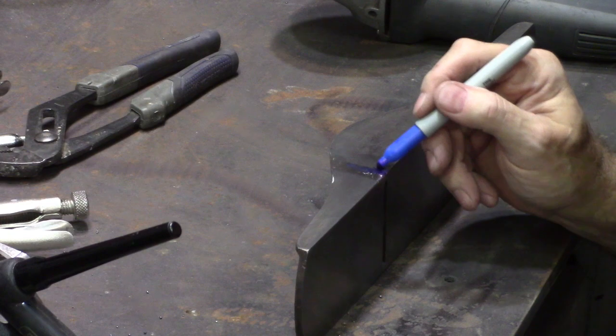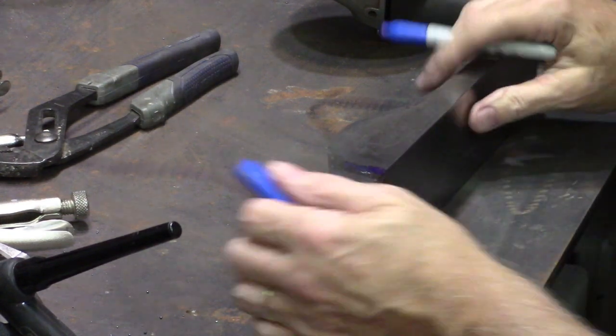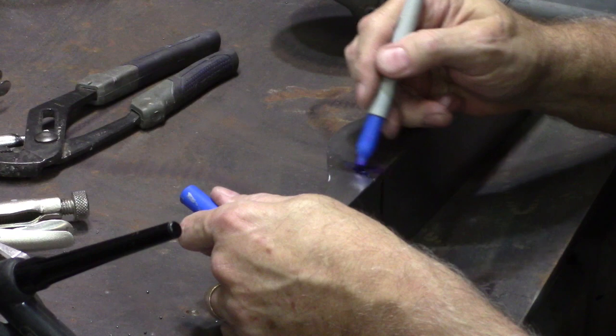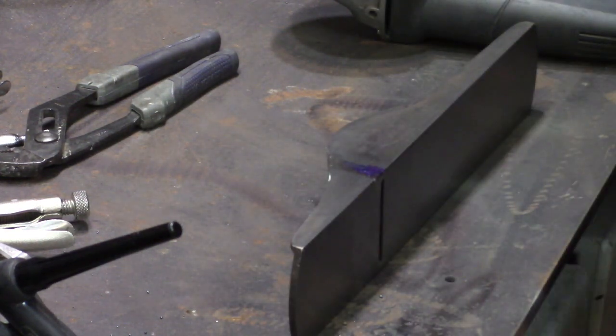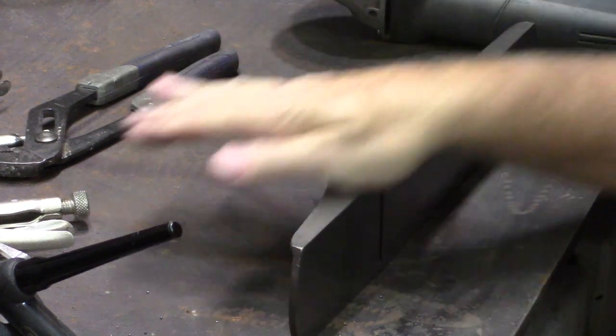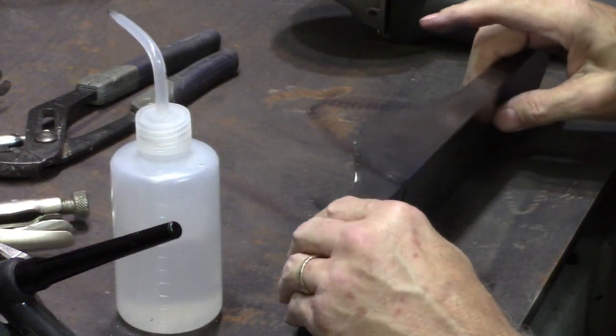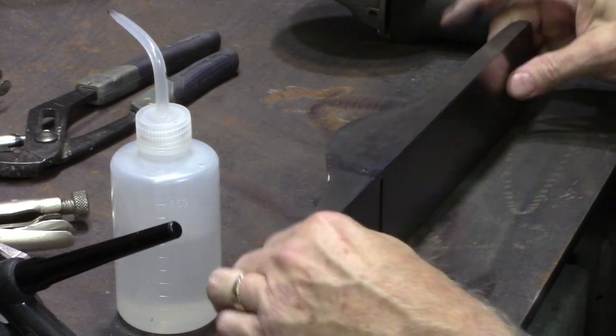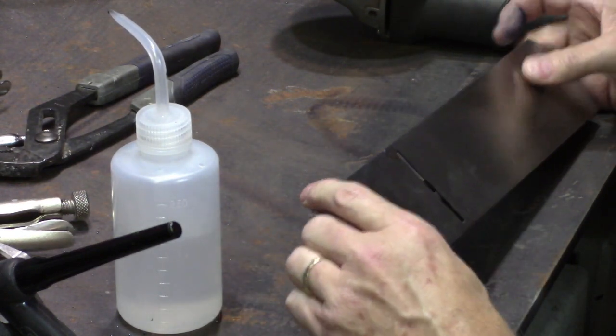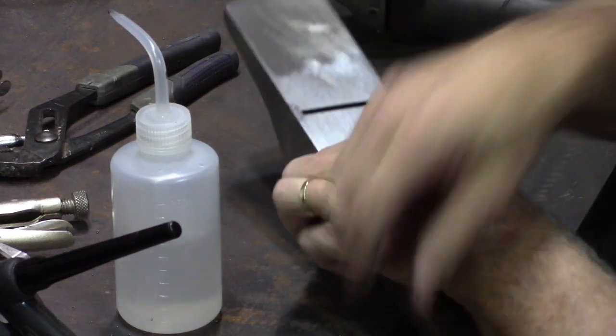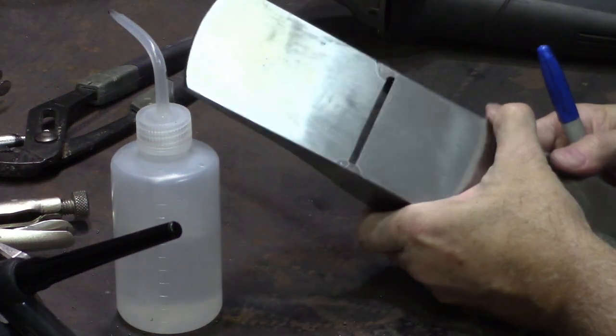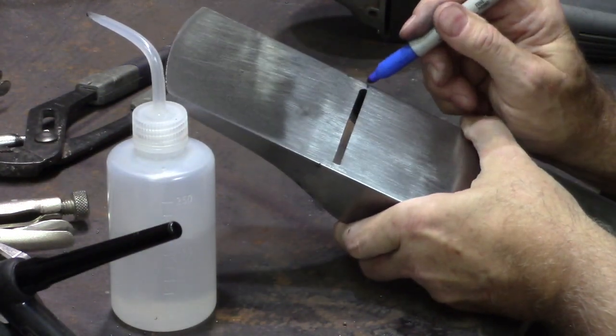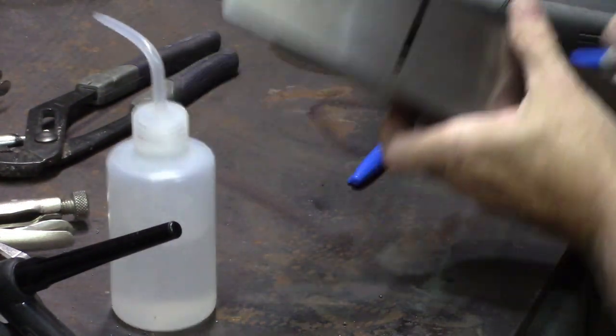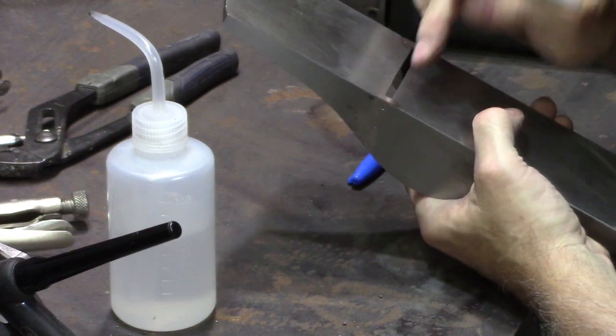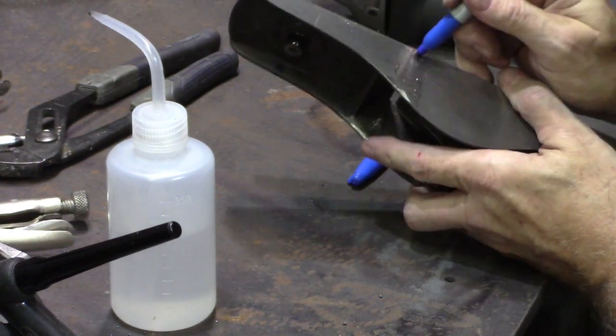Now here's a quick tip. This is a poor man's Magnaflux. If you're looking for cracks in a weld and you don't have a fancy Magnaflux system, what I use, and works really well, is just a Sharpie marker and a little acetone. You kind of saturate the area you want to check for a crack with a Sharpie, and then put just a few drops of acetone on it, and the acetone will thin that Sharpie down. It will flow into all the cracks in the material, and it will highlight them fairly well. And as bad as my eyes are, I can still find a crack with this method. It works really pretty good.